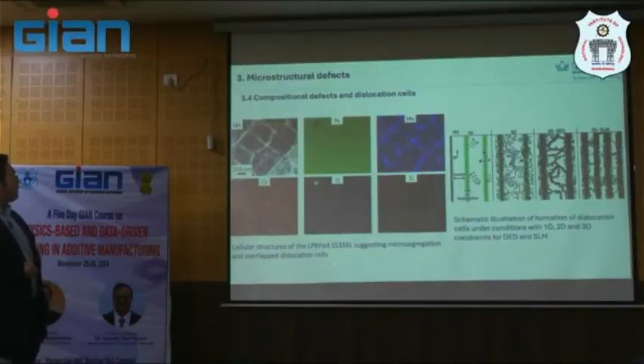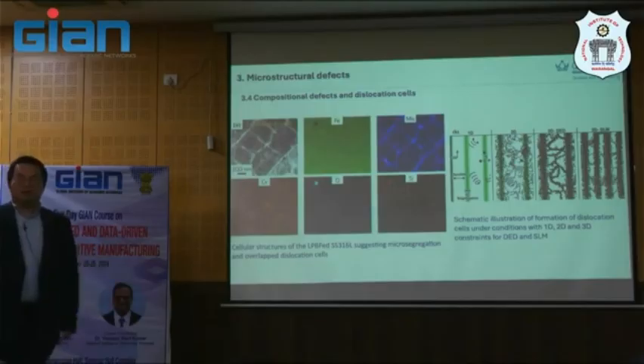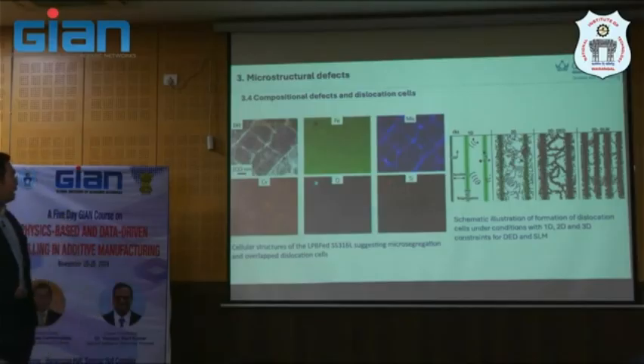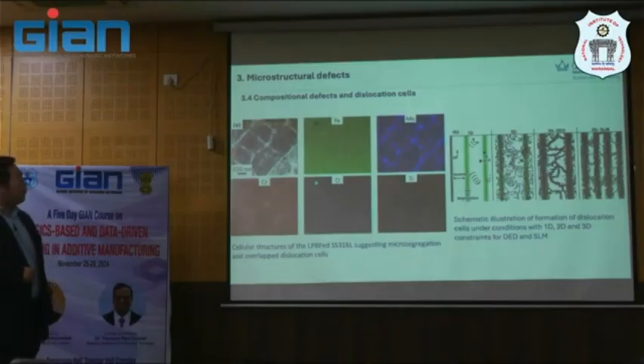This is a cellular structure of LPBF stainless steel 316L. So it is a commonly used steel for 3D printing. And you see the suggested microsegregation overlapping the dislocation cell. Sorry, this will go deep into metallurgy, but it's quite interesting science that we can look at the grain boundary. This is actually decorated at that location. And this is because of the formation of dislocation cell at the condition.